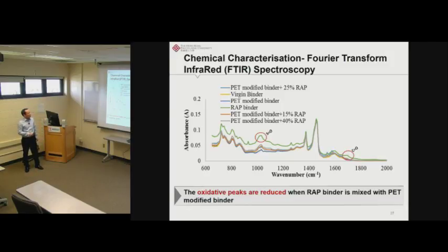From the FTIR spectrum, we notice that the oxidative peaks are reduced when the wrap binder is mixed with the PET modified binder. This somehow indicates the PET additive even has a certain rejuvenating effect. But we still need to probably do more tests, first to verify whether this is true, and if it's true, we need to find out what's the reason behind. This is really good. If we add the additive into the wrap mixture, it provides the rejuvenating effect and also serves as the anti-stripping additive. It really helps our wrap mixture.